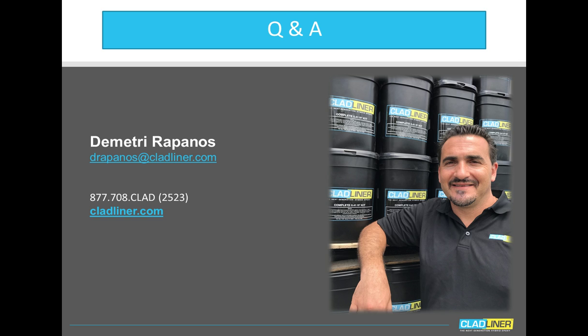Well, the best choice, if the manhole itself was very badly degraded and you would need more structural capabilities, putting on 2 inches of the hybrid epoxy, while technically would work, would become economically infeasible. So at that point, we would recommend that a rebuild gets done first with a restore product like the Clad Restore before the hybrid epoxy is put over as a liner.